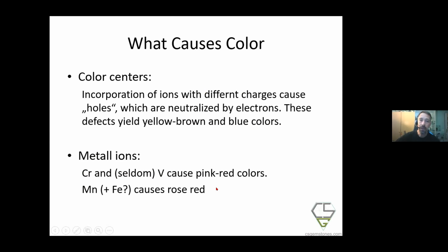And some rose red specimens have already been found that do not contain the chromium, but they have manganese and maybe some amount of iron 3, which typically causes yellowish color. But if you mix the two primary colors, like we have the chromium, which is red, and some color centers, which are yellow, you get the orange, which Ouro Preto is known for.